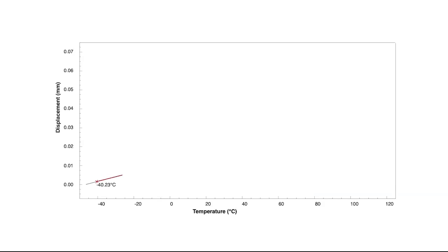At the low temperature portion of this graph on the left, you see the pre-TG CTE from -40 to 0 degrees C of 61 parts per million. As the temperature increases to the right, you see an inflection point on the graph at about 60 C. This is the TG. Below this temperature, the polymer is considered a rigid polymer, and above this temperature, the polymer is a soft, pliable polymer.